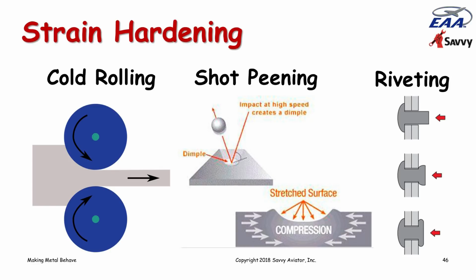Typically, something like a connecting rod is hardened by shot peening. A real good example of strain hardening is the humble aluminum rivet, AD rivet, where it starts off pretty soft, but when we drive the rivet with a rivet gun, we're basically strain hardening the rivet, and so it becomes a permanent joint. The rivet is much harder after we've driven it than it was when it came out of the box. Again, because we're putting the material under compression and squeezing the atoms in the crystalline structure closer together in a way where they remain permanently deformed in that state.